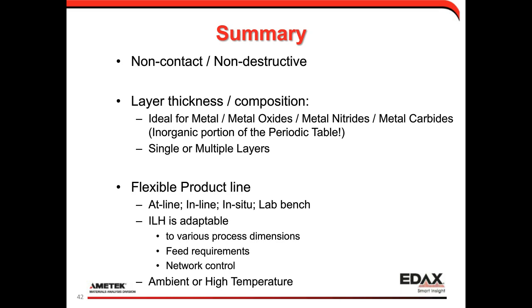Another question, does this work for aluminum oxide coating on an iron substrate? Yeah, it would also work for that. In this case, we would put in whatever the oxide stoichiometry is, and you can either measure the aluminum signal directly and, assuming a certain stoichiometry, get thickness that way. Or, depending on the thickness you're trying to measure, you can also measure the iron substrate signal, and you can measure a much thicker aluminum oxide coating.